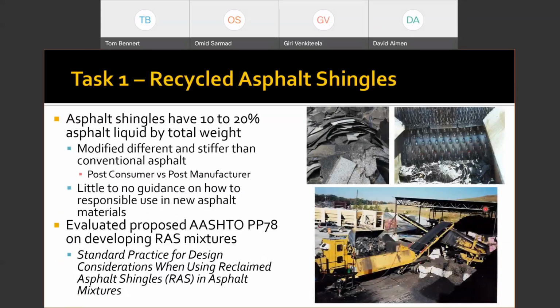Again, we talked heavily about recycled materials. Now, this was a particular project where New Jersey DOT had allowed the use of what they call recycled asphalt shingles, as long as they were what we call post-manufacture. Now, for those of you that have never heard this before, recycled asphalt shingles, or asphalt shingles in general, have about 10 to 20% of asphalt by total weight. They also have some fibers in there. They also have some coarse sand in there, some granular sand in there. But they have about 10 to 20%.